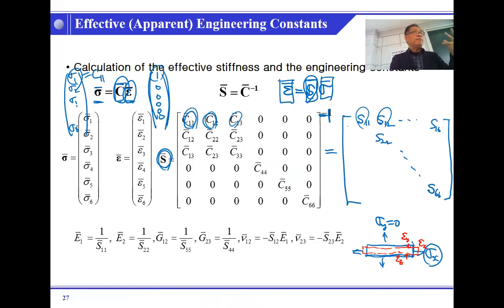Experimentally, it's not possible. Well, this is a very simple observation, but critical for understanding material property. So the way we apply the stresses, sigma xx and sigma z, and even sigma xy equals 0, and sigma zy and zx, all 6 components, we are applying stresses, okay? And so whatever we measure are the strains, which are directly the terms of compliance.